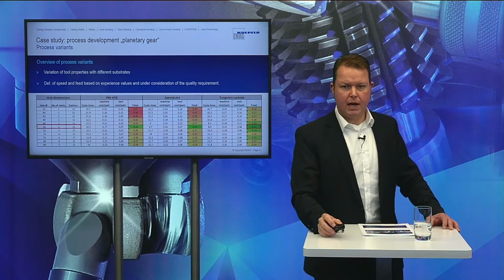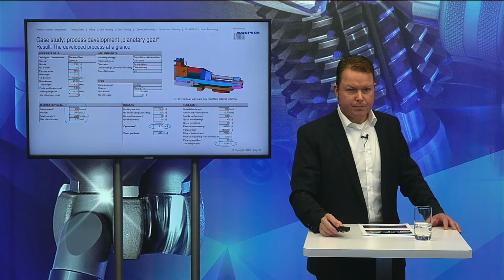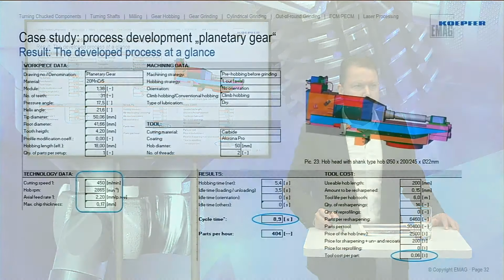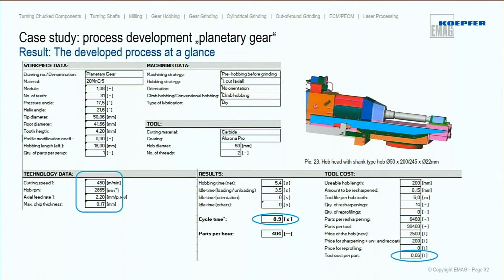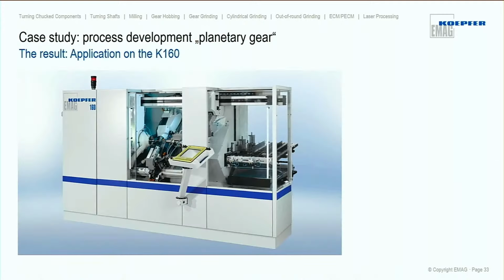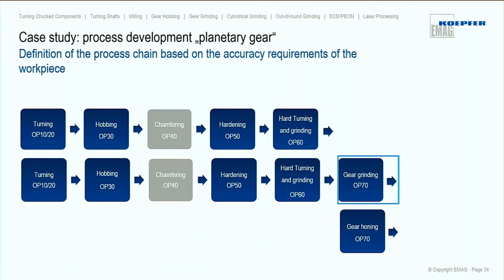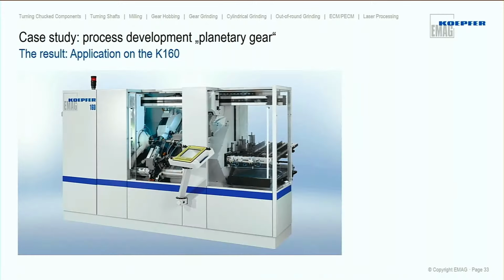And we have realized this also. You see here an overview of the developed process at a glance. We see the cutting speed that we really apply. It's 450 meters per minute, feed rate 2.2 millimeters with maximum chip thickness 0.17, and the cycle time is less than 9 seconds. And this is how it looks like on the K160 in reality. I think we need to get this movie started.